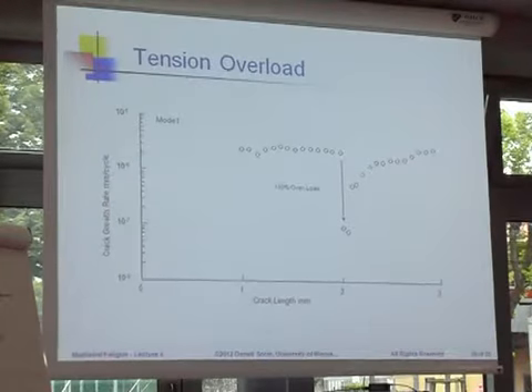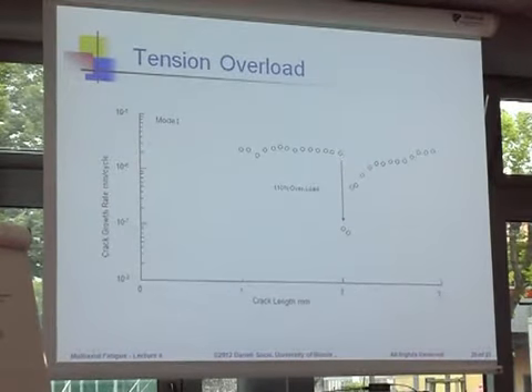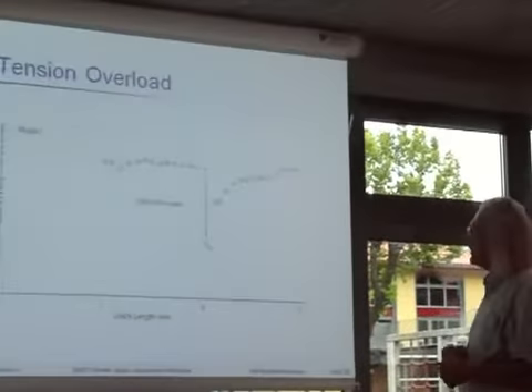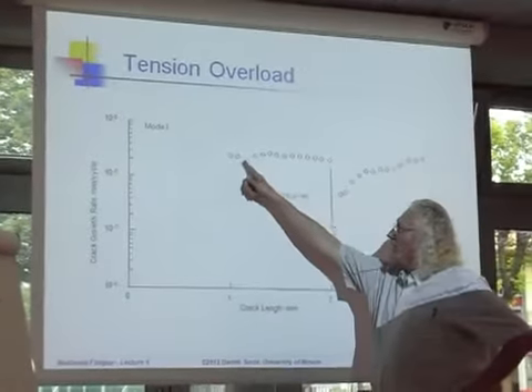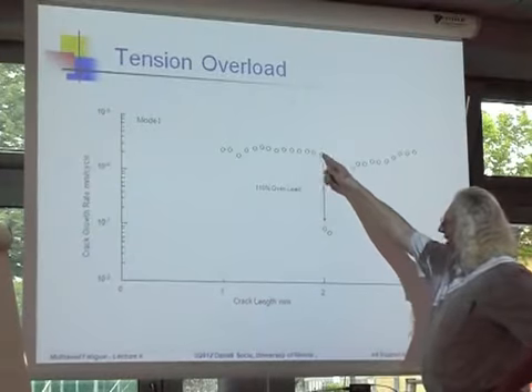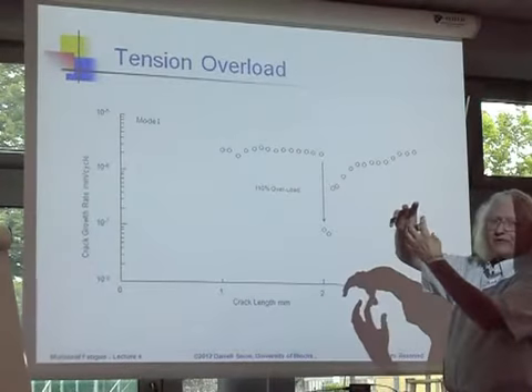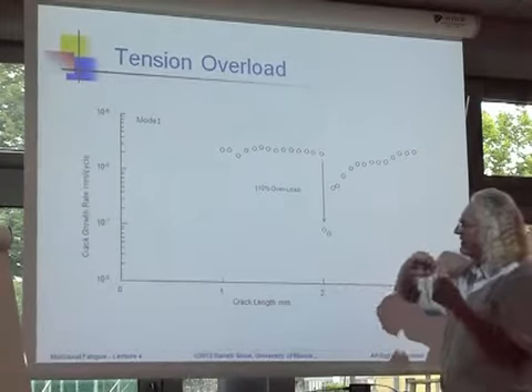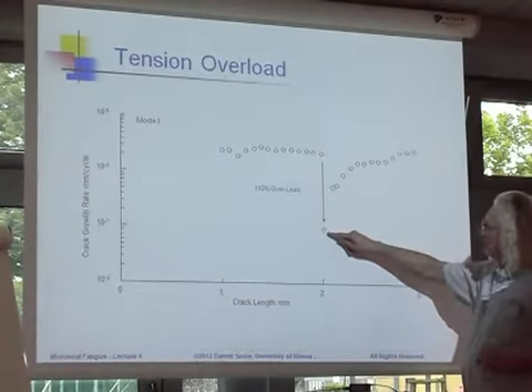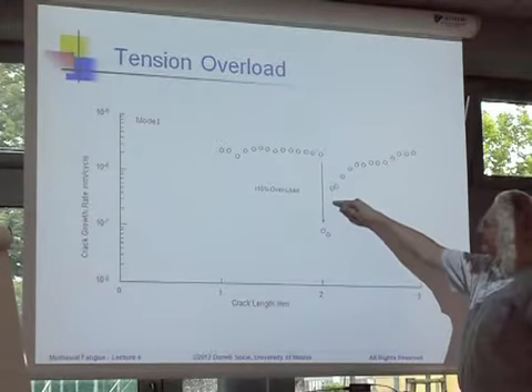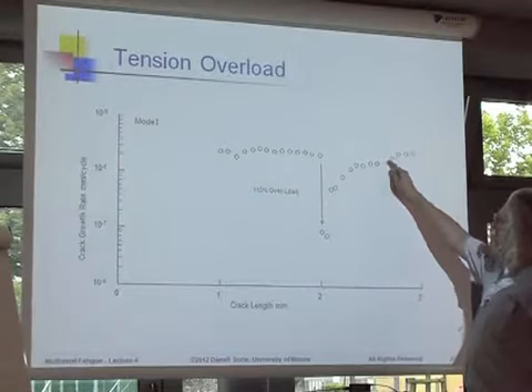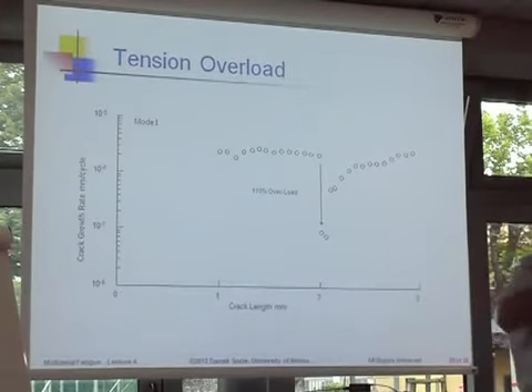Okay, let's look at a few other things that happen, just to try to compare the behavior in mode 3. By the way, that kind of interlocking is unknown in mode 1. There's no concept of this interlocking, no concept of that kind of friction, or of the debris in mode 1. If we look in mode 1, then of course if you have a tension overload, what you find is we're growing with a constant growth rate, and after I have a tension overload, I introduce these favorable residual stresses in front of and behind the crack, and the growth rate decreases by maybe 2 orders of magnitude, and then as the crack continues to grow very slowly, it slowly recovers to the normal growth rate. And that's our expectation in mode 1.